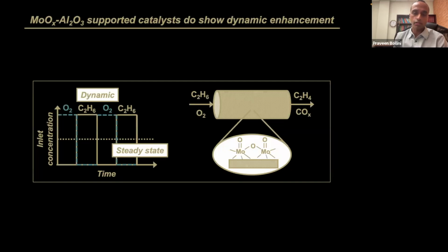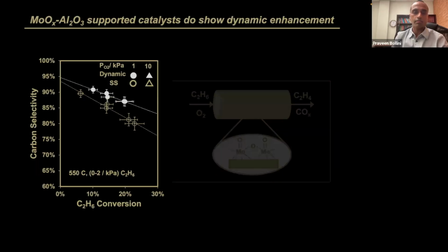And so what I'll show you again briefly in the interest of time is that you can, in fact, increase your selectivity to light olefins such as ethylene and propylene by operating in this dynamic mode rather than at conventional steady state. So I'm going to show you briefly a data set where you expose a supported molybdenum catalyst to oxygen, then ethane, then oxygen, then ethane, and you obtain a higher selectivity compared to your conventional steady state operation.